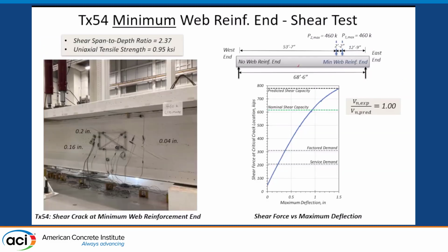For shear, we do have 2 shear tests, 1 at each end. So you can see in the schematic here, we're moving to the minimum web reinforcement end to test, and we actually are loading up to 460,000 pounds per actuator at that end. And that gives us a total shear of almost 800,000 pounds across that web as we went to the maximum loading. We did get some cracks, of course, as we got to those high loads.